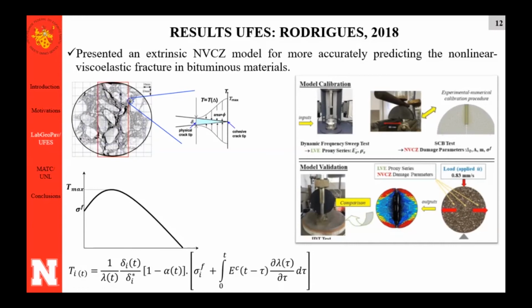The model that she used is the nonlinear viscoelastic cohesion model proposed by Allen. In this model, it considers the traction separation curve in the cohesive zone as nonlinear, as you can see here. That's why the model is called nonlinear viscoelastic, it has viscoelasticity included. And the model is extrinsic because the cohesive zone only starts after a certain level of stress, it does not start from zero.